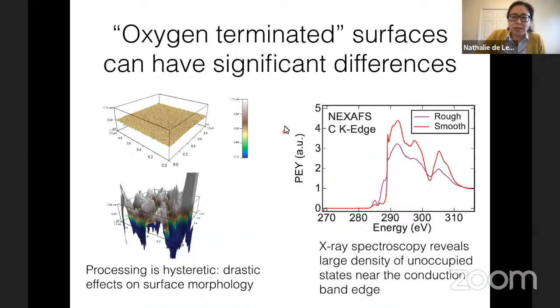So one of the things that we saw immediately is that a lot of people in the community were using oxygen terminated surfaces, and then they would just say, we oxygen terminated the diamond. But what we found was that depending exactly on the method of oxygen termination you use, and specifically depending on the surface morphology, you can have enormous differences in the characteristics of the surface.